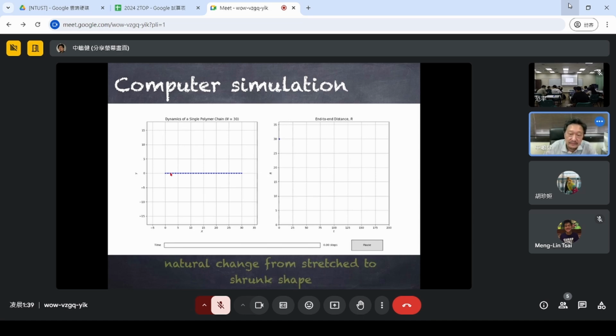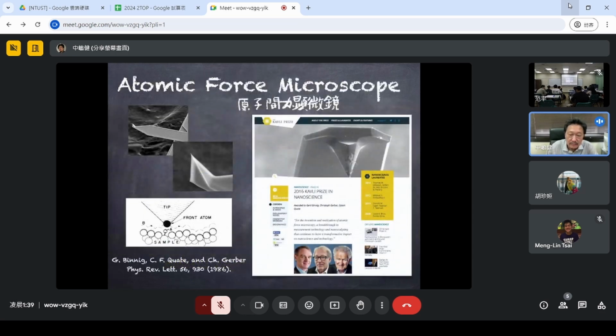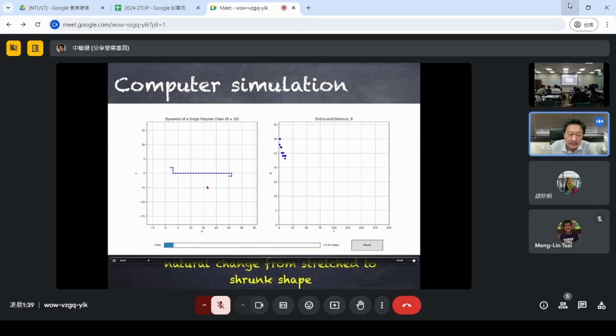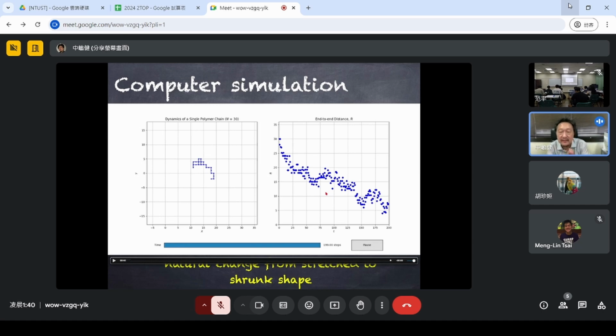Then what's going to happen? Oh, why doesn't it move? Oh yes, it starts to move. So first both ends start to move, and now many of the components have some freedom. Then finally it gets into a shrunken shape. The size also goes from 30 to a smaller value, and actually this small value should be the root of 30, so like 5 to 6. So it actually came to here. Okay, so this is quite natural. The elongated component gets to a small shape. So this is a natural trend.